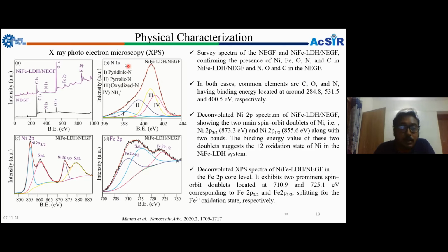But the other forms that are forming, the pyridinic nitrogen and the pyrrolic nitrogen, are helpful for electrochemical activity. The oxidized nitrogen is present in higher percentage here, and secondly the pyrrolic nitrogen, which is very responsible for any kind of electrochemical performance. And that nitrogen can help hydroxyl ion adsorption during the electrochemical performance.